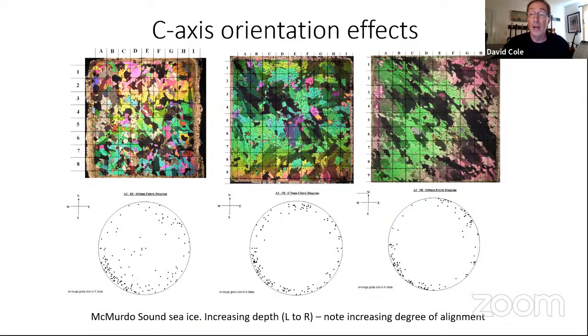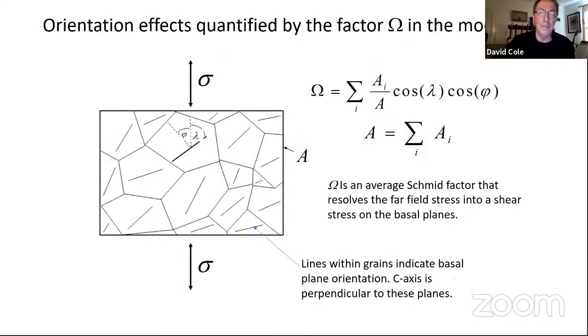But frankly, this is not that strong of an orientation. We've seen much stronger. But we want to account for that orientation change simply because once it develops, then our ice in the horizontal plane is no longer statistically isotropic. The resolved shear stress on the basal planes is going to be an increasingly strong function of the direction in which it's being loaded. So the way we handle that in the model is essentially calculating an average Schmid factor, which is basically a factor that takes the far field stress and determines the average resolved shear stress on the basal planes.